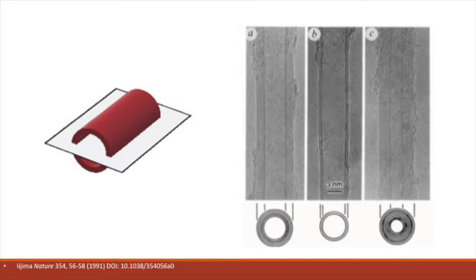All of the nanotubes were multi-walled, which means that the nanotubes had smaller nanotubes inside of them, similar to Russian nesting dolls. The number of nested tubes that were observed ranged from 2 to 50. The thinnest nanotube that was observed was composed of 2 nested nanotubes, whose inner diameters consisted of 5.5 nanometers and 4.8 nanometers. The 2 nested tubes were separated by a distance of 0.34 nanometers, which is the exact distance between 2 sheets of graphene within a sample of bulk graphite.